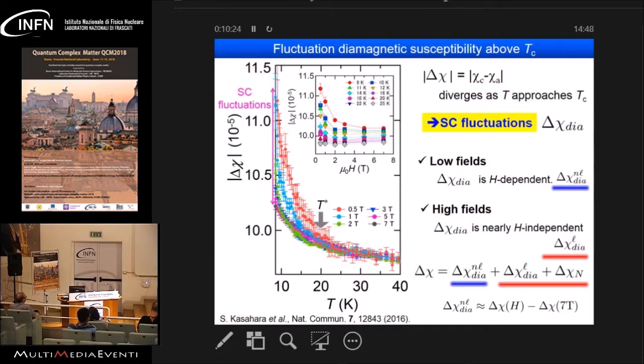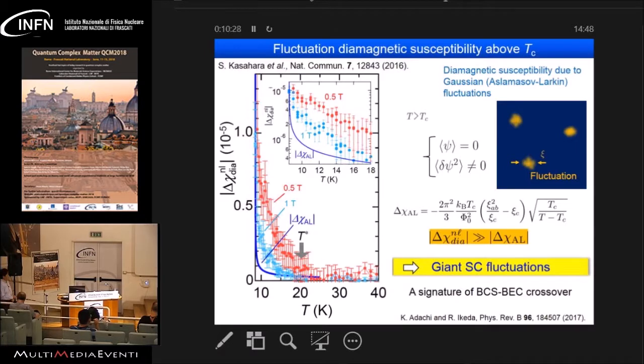And we can analyze these superconducting fluctuations by comparing with a conventional Gaussian type fluctuation. And this is given by this kind of Aslamazov-Larkin type expression. And we compare our data with this theory curve. And as you can see, these theory curves deviate from the experimental data. Our data shows a much larger diamagnetic signal than expected by the theory, okay? And I should mention that this theory curve is for the zero field limit. And as you can see, we have a tendency that if you go to lower fields, it gets more enhanced, meaning that our data suggests quite giant superconducting fluctuations compared with the conventional Gaussian type fluctuations.